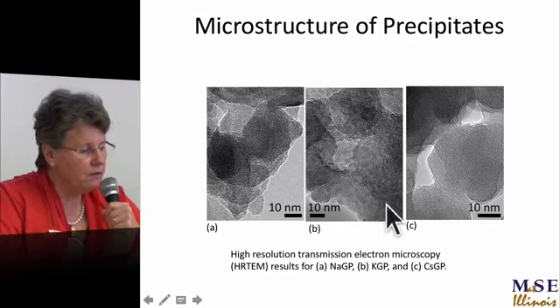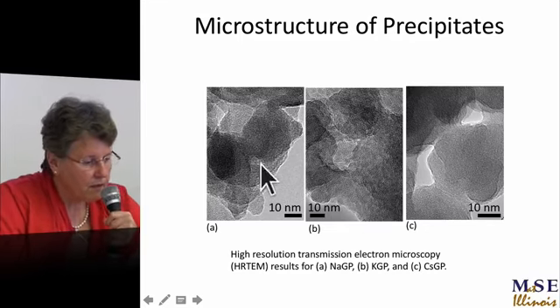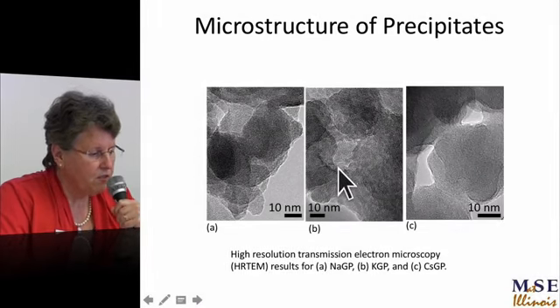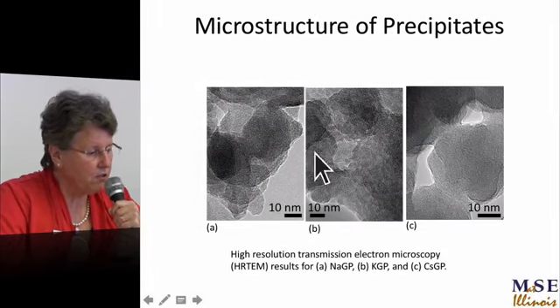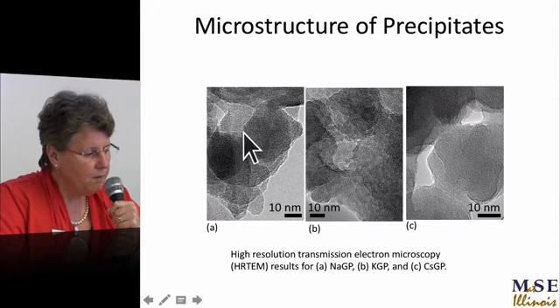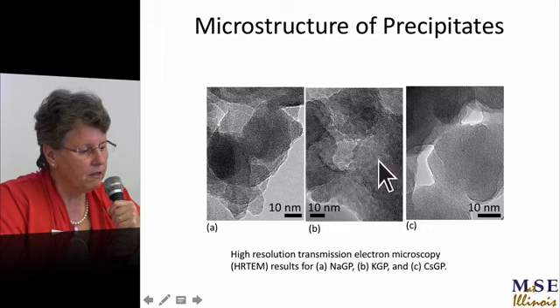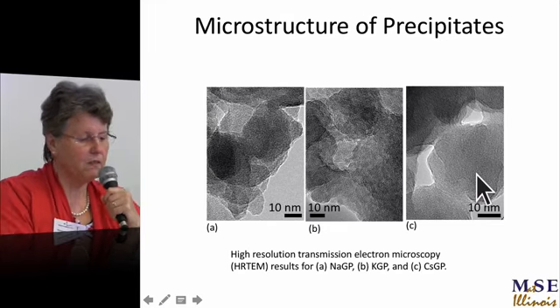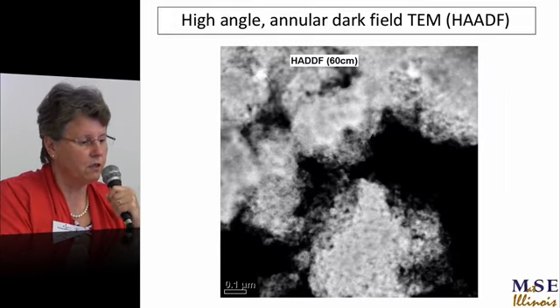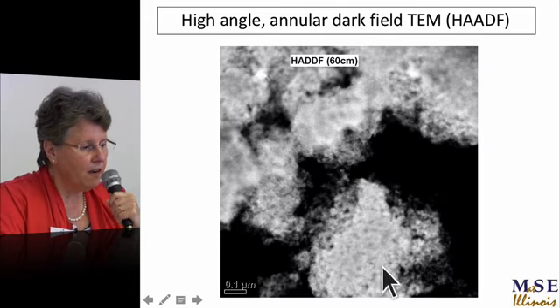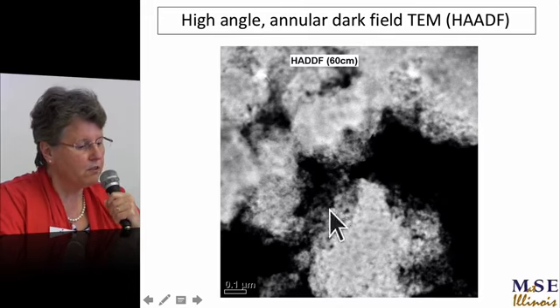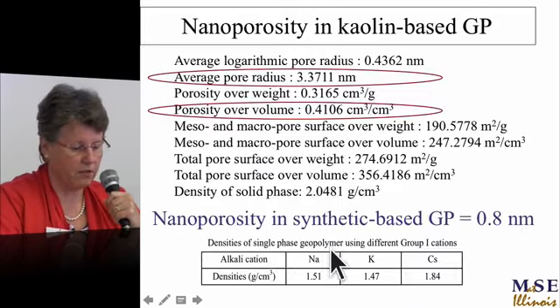And if you use sodium or potassium or cesium, they've got texture, a little black and white, you know, I don't know, but it's beyond the limit of TEM by now. And there's texture inside a texture inside a texture, and this is sodium, potassium, cesium. Maybe sodium's like 30, 40 nanometer splats, these little splats and precipitates that stick to each other. And then a high angle annular dark field, it's nanoprecipitates. You can see those little pancakes just sitting on top of each other, but it makes a tight, coherent structure.